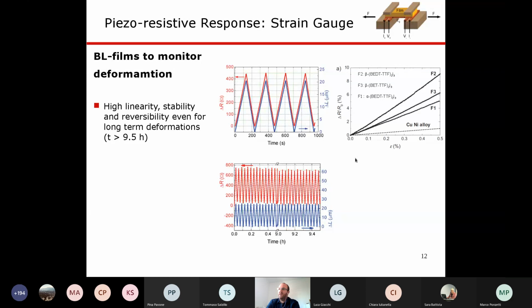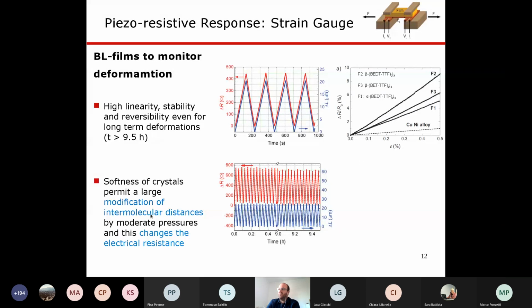If we plot the change of the resistance as a function of this elongation, we see a very nice linear response. And in a very in-depth analysis, we actually checked the crystal structure of these materials with a technique called XRD analysis, which I will describe a little bit later in more detail in the humidity sensors. This is a technique that allows us to measure the distance between the molecules. And what we saw is that when we deform these films, we change these intermolecular distances, so we take the molecules a little bit farther apart. And this is responsible for this nice resistance change we see. They are really, really sensitive.